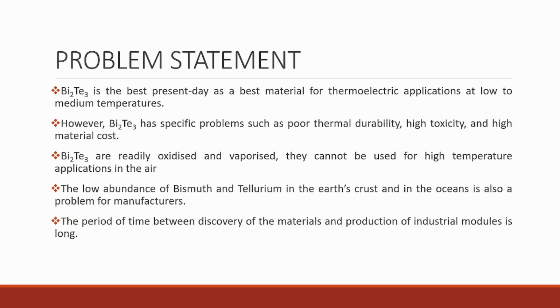The problem in this research is bismuth telluride is the best present-day material for application at low to medium temperature. However, this material has specific problems such as poor thermal durability, high toxicity and high material costs. Bismuth and tellurium are readily oxidized and vaporized. They cannot be used in high temperature applications.